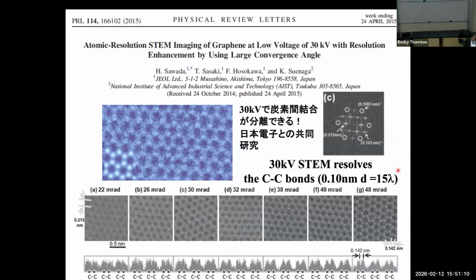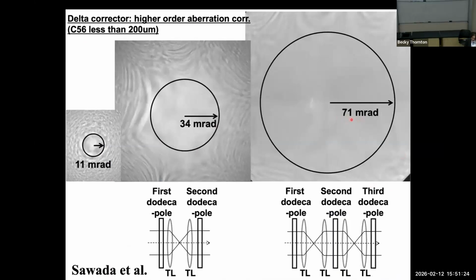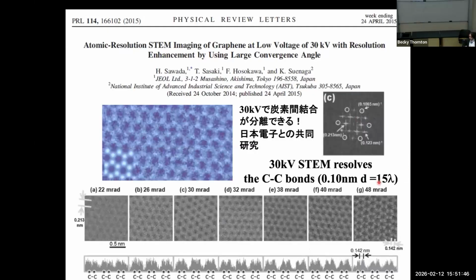Yes, and if you calculate that, this is 15 times the wavelength. So it's still something we can improve. Okay, simple calculation. This is the CTF, the first zero. If you go to 1000 milliradian, in this case you can get the resolution of the wavelength limit. Okay, but still we have only 71. So it means we could get up to around 15 times the wavelength limit.